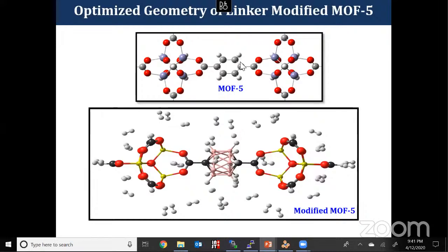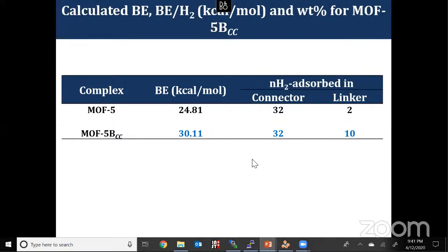Then we calculated the binding energy as well. The connector parts, both modified and pristine, adsorb a similar number of hydrogen molecules. But for the linker part, as I mentioned, there is an advantage of using carborane, and you can get more hydrogen molecules in the linker. That will also help to improve the material quality